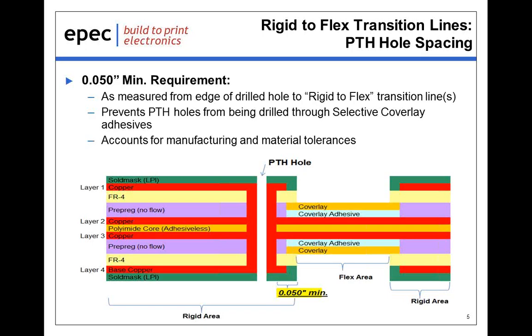The first element in the Gerber layout that needs to be conformed to is the spacing from plated through holes — be them PTH or component holes — as measured to the rigid-to-flex transition line. Maintaining this 0.050 inch minimum requirement ensures that the vias are not being drilled through the cover lay that will engage the rigid areas. This spacing accounts for the accumulation of all of the various manufacturing and material tolerances present in the process, and by eliminating the vias from being drilled through the cover lay, dramatically improves the reliability of those vias.